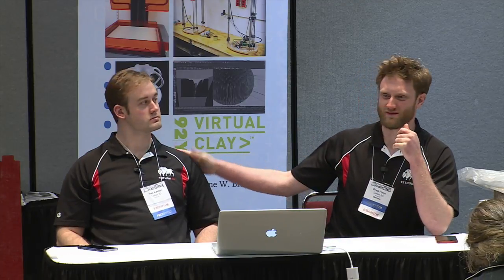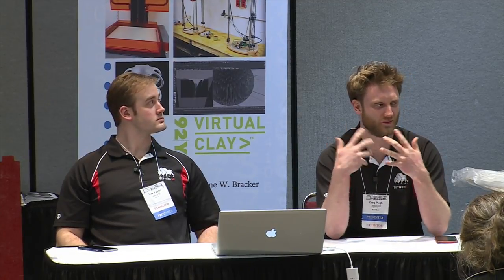We also bisque to cone 6 with our material. I'm going to call Max out, it's a joke we have, but Max is a very digital ceramic artist, and we fast fire to cone 6 for a bisque, and Max thinks that's pretty normal for ceramics. It's a different way of thinking. You can't blow up our material. You can fire it pretty much as fast as you want. I haven't been able to fire it fast enough. There's a lot of things you can do to it that you can't get away with in traditional ceramics. We're attaching things together at cone 6. You have a durable object, but you can put it together past cone 6, and that's pretty remarkable. You could probably do it past cone 10. I don't fire to cone 10 often.